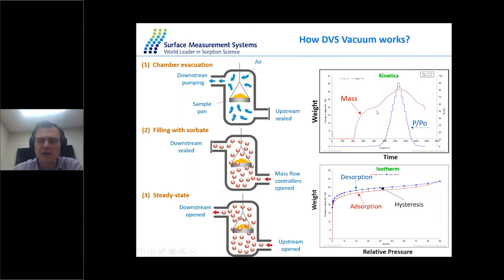On the right-hand side, I get my kinetic plot from the entire experiment. This can be used to understand the actual contours on the left-hand side. During the drying stage, what you observe is mass loss. The sample is losing mass. When the sample is brought to the adsorption temperature, let's say from 300 degrees to 25 degrees, you cool down to 25 under high vacuum.